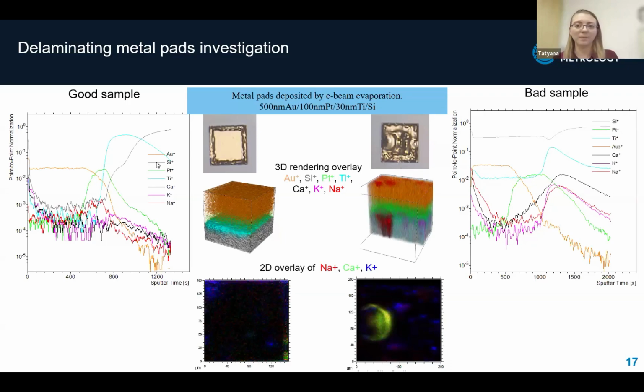The next example is a typical task for ToF-SIMS, comparison between a good and a bad sample. Let's start with the structure we analyzed. It consists of 30 nanometer of titanium, followed by 100 nanometer of platinum, and finished with a 500 nanometer of gold layer on a silicon substrate. Now let's look at the good sample on the left.